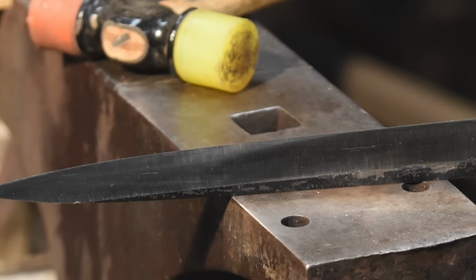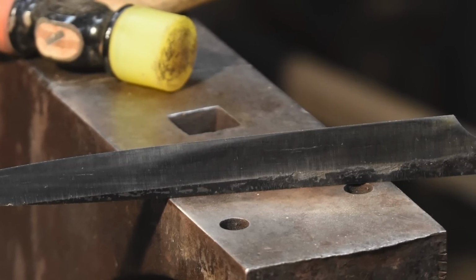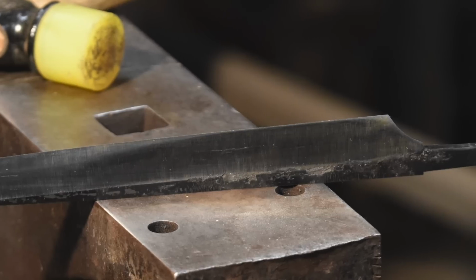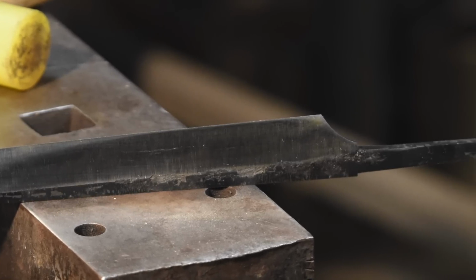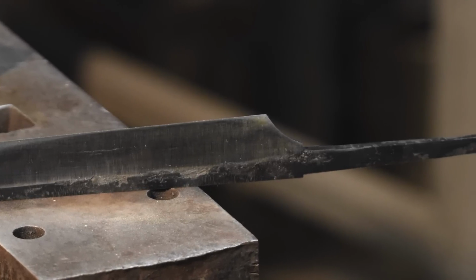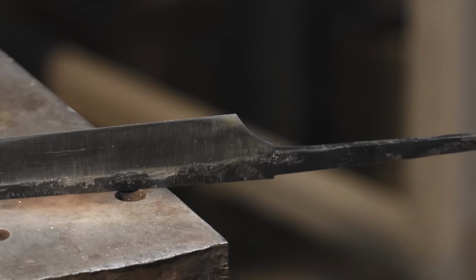And time for another screw up. In this case, it was just plain old inattention. Now, according to Japanese norms for how these knives are made, the bevel should be brought up more or less to the bottom of the tang, essentially where it was at the time of heat treating. But I let my attention slip for about half a second and the bevel crawled up another 1/16 of an inch.